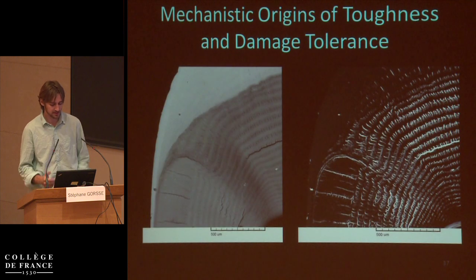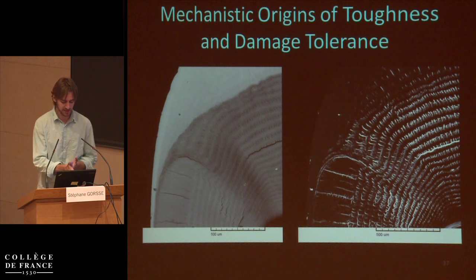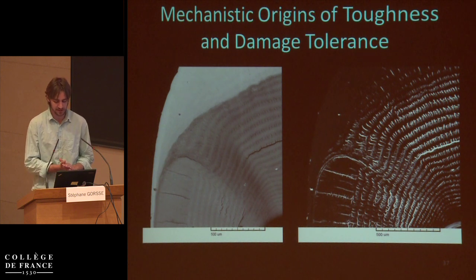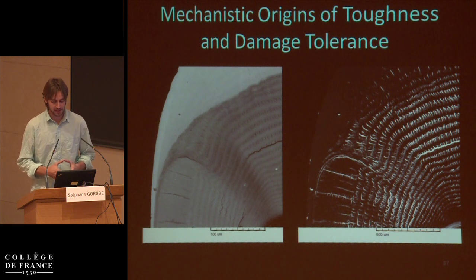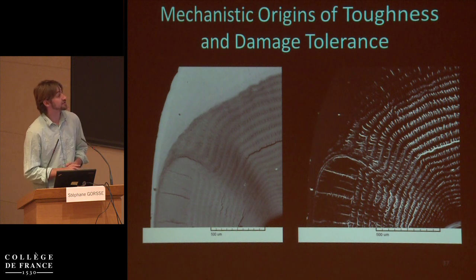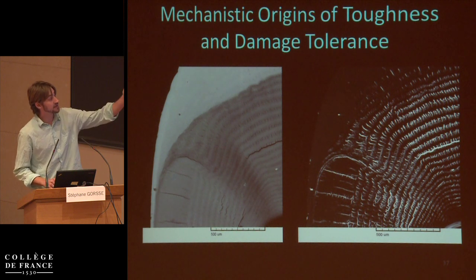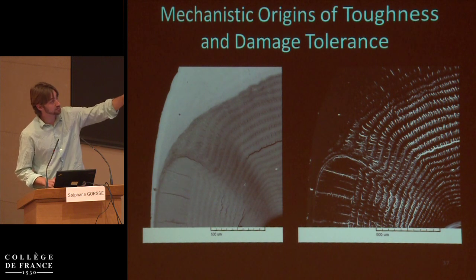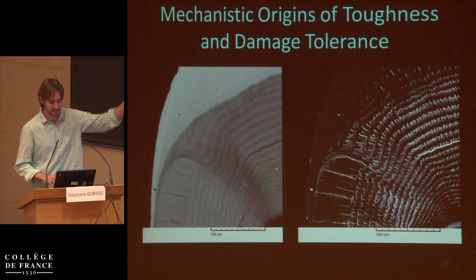And so when we look at this charge contrast image compared to the backscattered image, it allows you to very easily see all of the microfracturing occurring within the sample. And you know, this looks to very much confirm exactly what we're saying, where you have these arresting domains. So you have these little microfractures appearing, but then getting arrested.